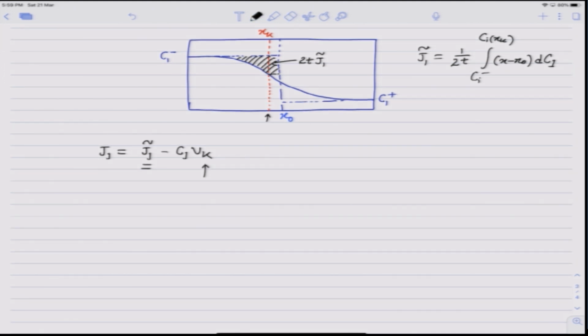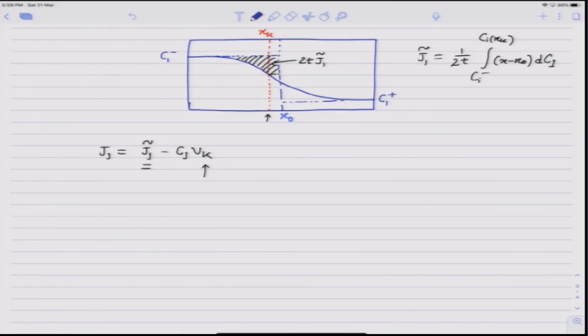Now these marker planes are usually travelling at a constant composition, and in an infinite diffusion couple we know each composition plane is moving parabolically with time. In other words, we say C is a function of x over root t, where x over root t is the Boltzmann parameter lambda. So we can also write x is equal to lambda root t.